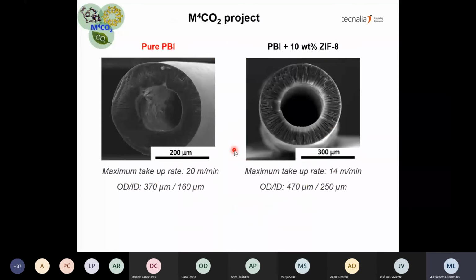So in this slide, I am showing the SEM picture of both pure PBI and the mixed matrix membrane developed in the M4CO2 project. During this project, in the spinning process, we were able only to increase the take-up rate up to 20 meters per minute for the pure PBI and up to 14 meters per minute for the mixed matrix membranes. And this leads to hollow fiber with quite big diameter. The diameter for the pure PBI was 370 micrometer and 470 micrometer for the mixed matrix membrane.